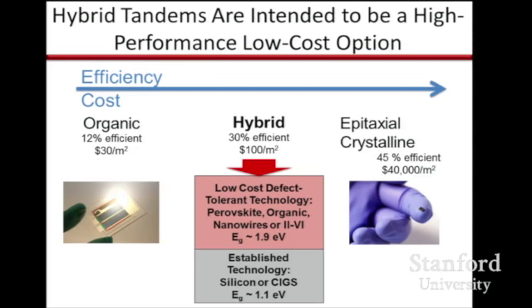So what I'm a big proponent of is finding some way to build a tandem solar cell that does not require slow epitaxial growth of the second solar cell. And so my group is working on what we call a hybrid tandem. And the idea is that the bottom cell will probably be silicon or CIGS, because the bottom cell should have a band gap of 1.1 electron volts, and that's exactly the band gap of silicon. And also copper indium gallium selenide can give you that band gap.